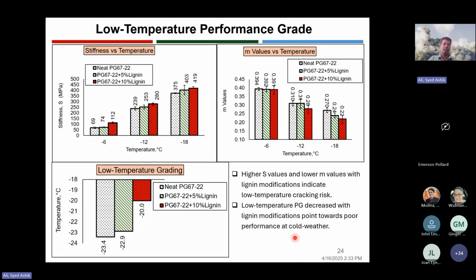Then, as I have mentioned, we wanted to see how lignin will impact the low temperature performance grade. We conducted the bending beam rheometer test and found two parameters from it. One is called the stiffness or S value. Another one is the M value, or the stress relaxation. So we have stiffness and stress relaxation. We conducted the test on the neat and lignin modified binders at -6, -12, and -18 degrees Celsius.